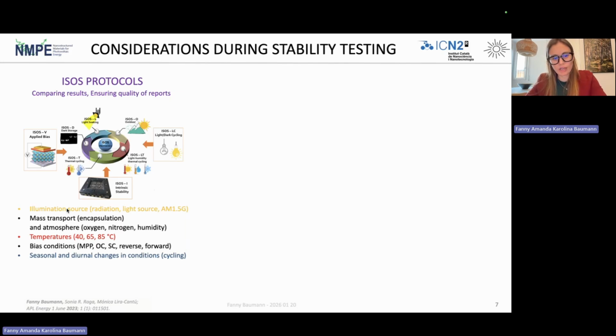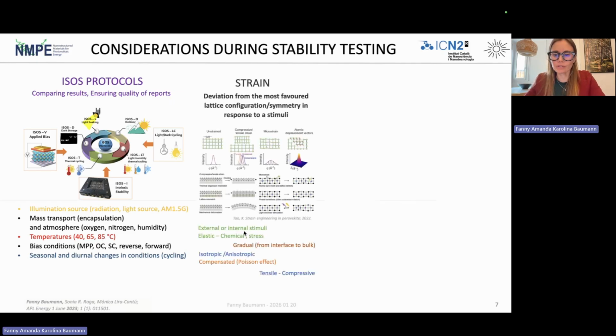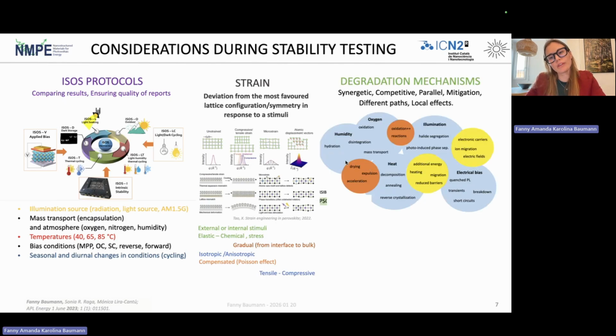We are going to use a light source that is closely approximated to the AM1.5G, though it's white LED illumination, and we're going to use 85 degrees Celsius during these experiments. We are also going to be mindful of strain throughout the devices and the evolution of strain over time during operation. Finally, we are going to think about the combination of different stressors applied to our solar cell. So in this case, we have illumination and heat. So we're going to be adding a lot of additional energy into our perovskite solar cell system.